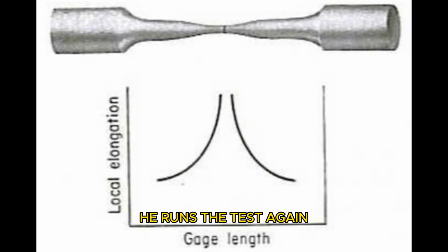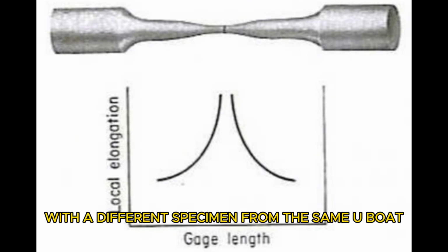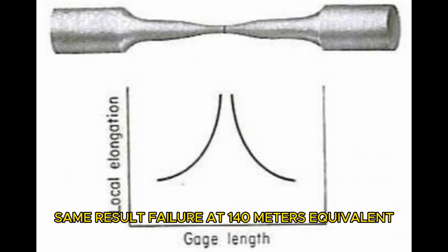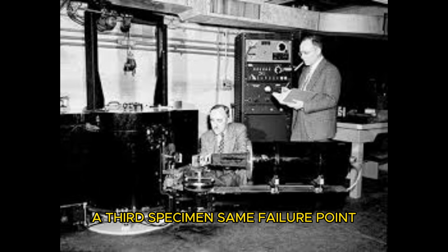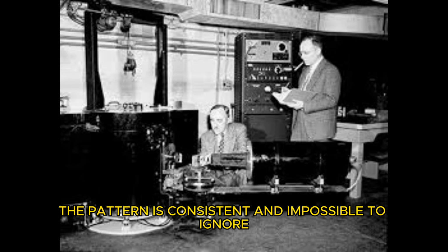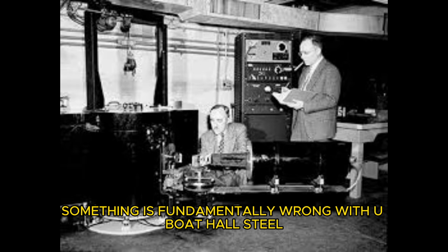He runs the test again with a different specimen from the same U-boat. Same result. Failure at 140 meters equivalent. A third specimen. Same failure point. The pattern is consistent and impossible to ignore. The steel is failing at pressures far below its rated capacity. Something is fundamentally wrong with U-boat hull steel.